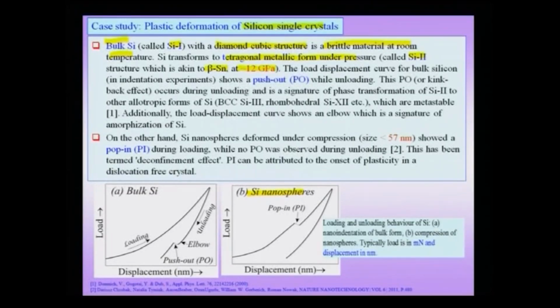Suppose I plot the load displacement curve for bulk silicon, which is load in indentation. This shows a very interesting feature. If you look at the load displacement curve here for bulk silicon, you see that during loading there is a nice smooth curve, but while unloading there are two important effects. The curve comes and there is an additional effect called the elbow. That means there is a sort of curvature change, and additionally there is an effect known as the push out or the PO effect, and this is observed only during unloading.